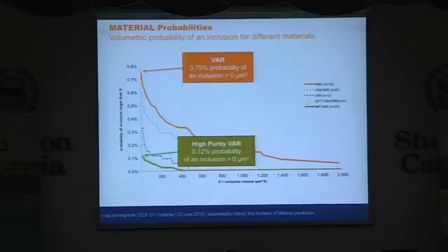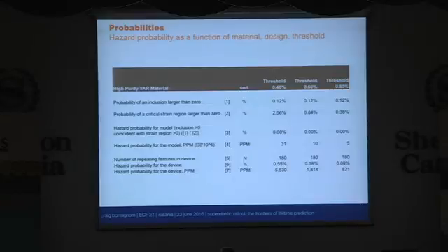And this is in the same terms as the volumetric probability that we saw for the material that we calculated earlier. And now we can put those two things together and do some math, right? And actually get to something like a percentage or ppm risk of these two things overlapping with each other. And this is a model that's still in development, we're still working here, but that can hopefully get us to something that can help us to predict fatigue lifetime as a function of material purity and the distribution of critical stresses within our design.